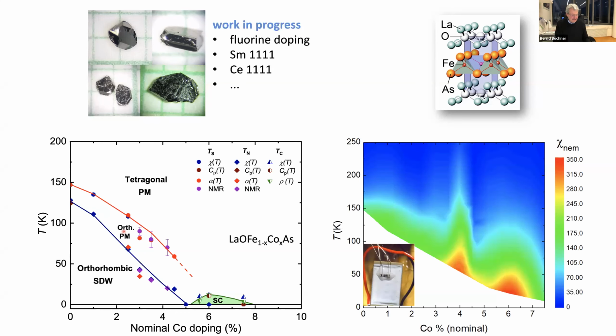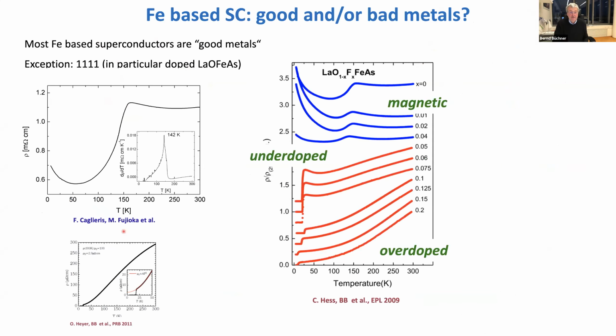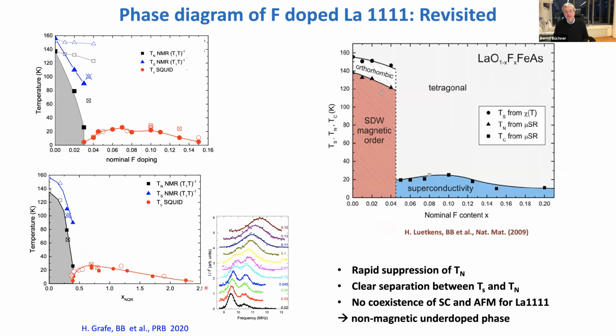And I think one possible answer is given by this figure here, the doping dependence: as a function of doping, we induce some additional sites here, some kind of disorder in this system, and that's characteristic for these 1111 type compounds, but that's another talk. So yes, it's an electronic instability, and the lattice picks it up, and the long-range lattice order is much more sensitive to an intrinsic kind of disorder. And finally, we end up with an electronic instability only. You still see this very nice boost of the nematic susceptibility, but without a long-range order of the structure.